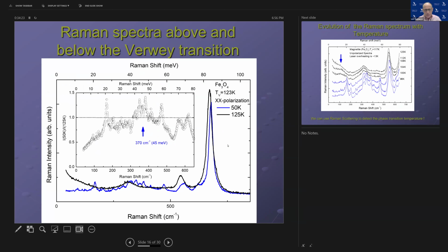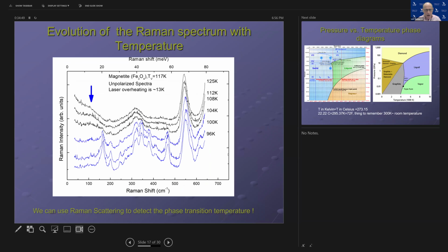Here's the graph of the magnetite spectrum, which shows one spectrum recorded at 125 K above the Verwey transition, in black, and another one at 50 K, in blue. What you can see immediately is that the blue spectrum has additional lines, and that's the indication of transition. And you can do a much finer job in studying this phenomenon.